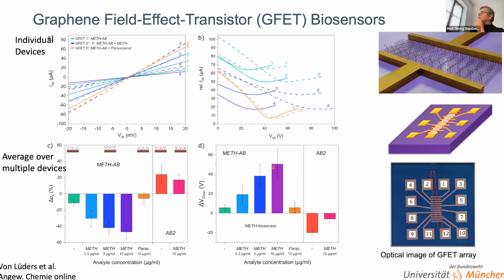And we have here the trend in the Dirac shift of the peak of the gated GFET. We used then as a check a different antibody which shouldn't react to meth, and indeed we didn't get the opposite reaction on this one. So that shows that our functionalization worked quite well and gave us nice results for a small molecule with very little cross-contamination, and we just published this paper in Angewandte Chemie. Okay, so this, I believe, shows that our functionalization route is quite successful.